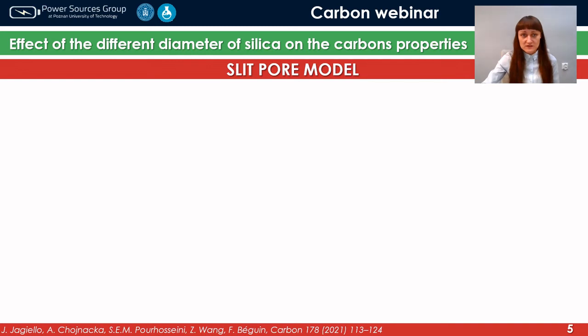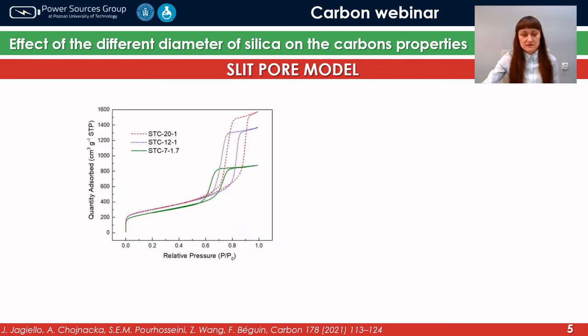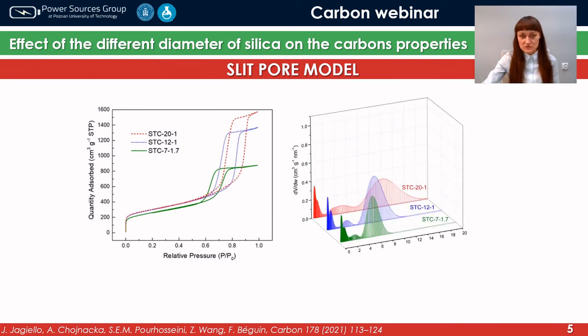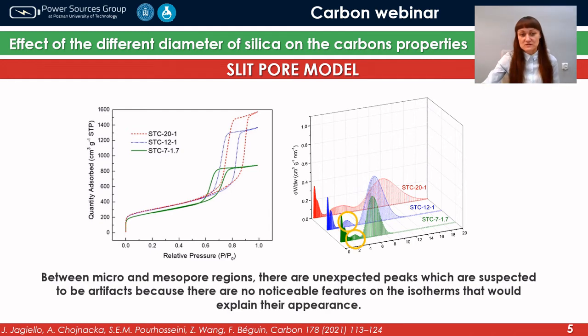First, I would like to show you the effect of the different diameter of silica on the carbon properties. As you can see here, for the samples in which we were using the silica template of 7, 12, and 20, all of the isotherms are characterized by the H1 type hysteresis loop, which closes perfectly at 0.6 relative pressure. By using the slit pore model, we calculated the pore size distribution, which shows 2 main regions: the mesopore region, which is of course connected to the used silica template, and also the micropore region, which is connected to the walls created by the pyrolysis of the glucose. And what is interesting is that between the micro and mesopore regions, there are unexpected peaks, which are attributed to artifacts because there is no noticeable feature on the isotherm that can explain their appearance.